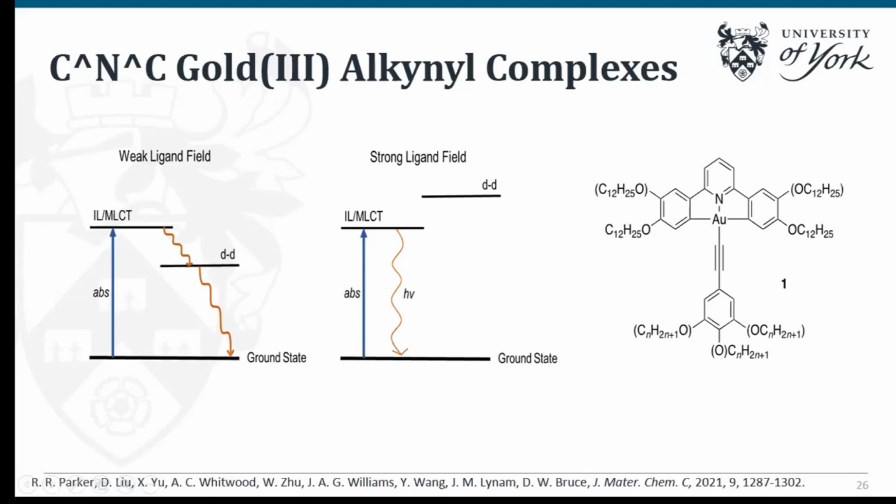However, it was discovered that when you put a strong ligand on it, such as this phenylacetylene ligand here, you could increase the energy of these metal orbitals, so that route where it could trickle back down to the ground state through them was no longer there. So when you excited these complexes, you would excite them up to the excited state, and then they would emit back down to the ground state. Hence, you've lit up gold(III).